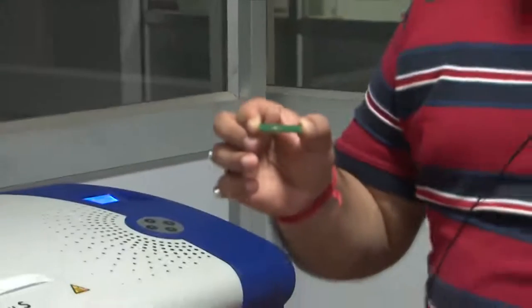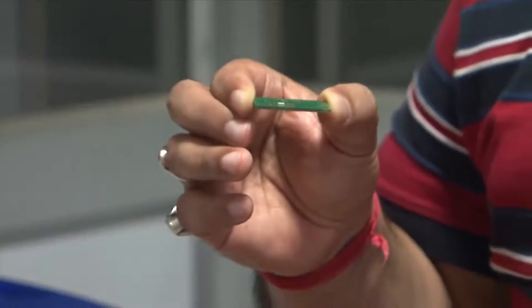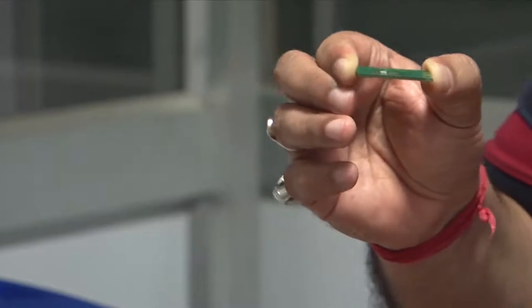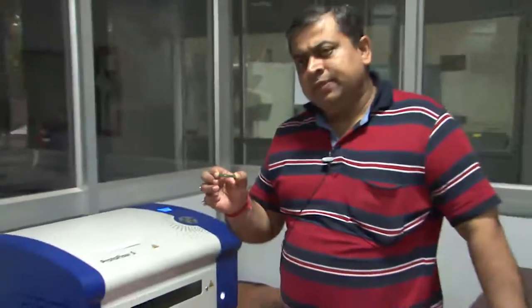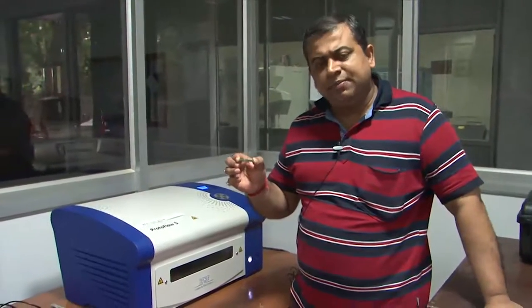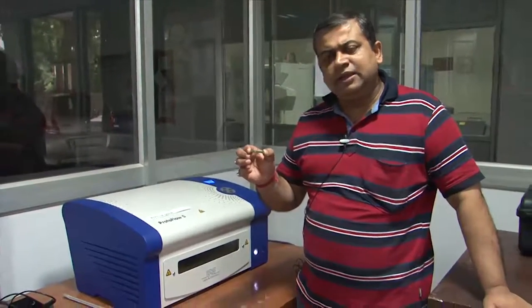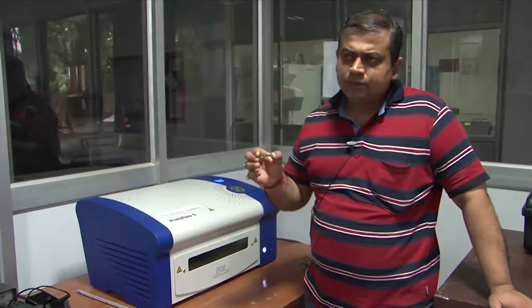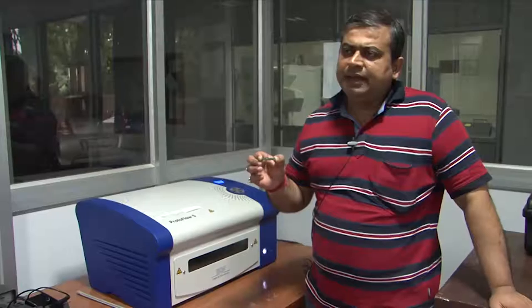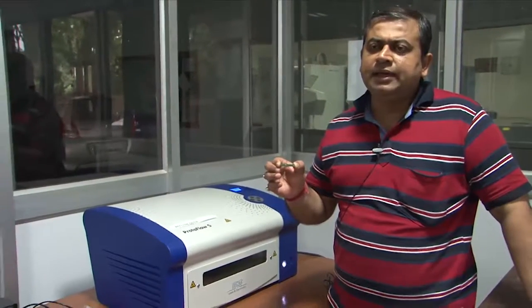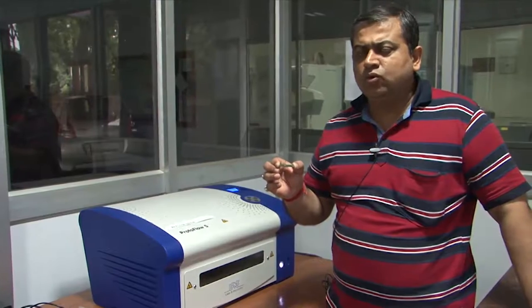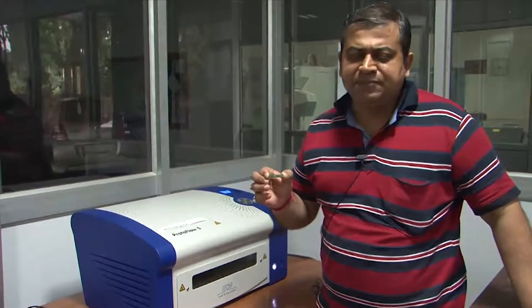There are three steps in this particular process. One is warming up the oven, where the temperature has to go all the way to about 190 degrees Celsius before the sample can be put in. That's typically the curing temperature of the silver paste being applied here. The other aspect is that the solder should not only go to that stage, but also reflow into the various gaps which are created. And even prior to that, whatever oxygen and air bubbles are in the silver paste, which come in during the application of the paste itself, have to be removed.